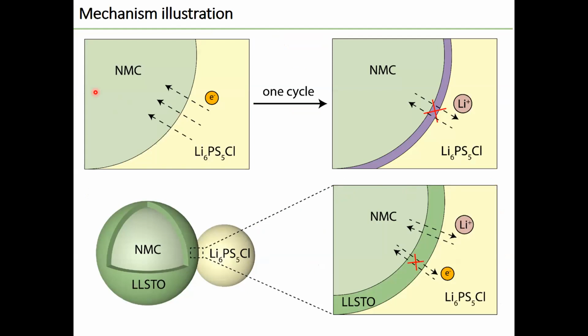For bare NMC, there are severe chemical reactions when directly in contact with the electrolyte. Meanwhile, during the first cycle, electrochemical reactions exist due to the electron conduction at the interface. As a result, both NMC and the electrolyte will decompose, and the interface resistance is highly increased due to the low ionic conductivity of the decomposed products.